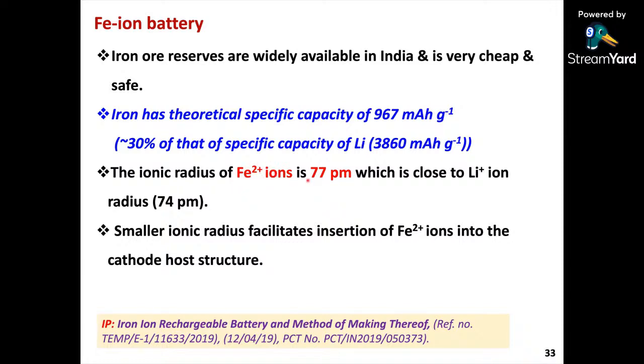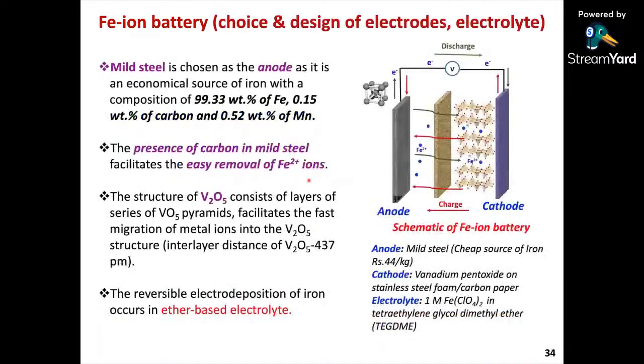So it is easy for you to intercalate Fe2+ at the cathode if you use a proper cathode. So what we have done is that this is an anode containing Fe. People have tried different types of Fe, but we use a mild steel as the anode, and it contains a small amount of carbon, 0.15% of carbon. We have used different types of iron, but we were successful only with this mild steel because of the presence of the carbon. It is possible for us to easily remove the Fe2+ ion, and at the cathode we used V2O5 on either stainless steel foam or carbon foam. And the electrolyte is 1 mole Fe(ClO4)2.